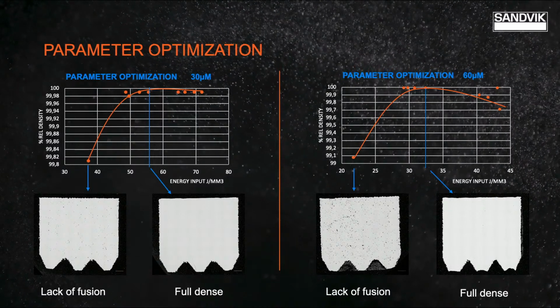All right. Well, so just to make sure that our viewers understand. So first we achieve the right quality, and that means microstructure, and then you increase the powder layer thickness. So that relates to the build-up speed. Is that correct? Yes, exactly. And of course, we do spot checks, doing tensile tests all along the way to get an outlook on the mechanical properties that we achieve.